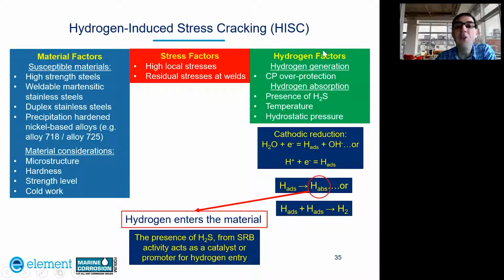So if we come to the hydrogen factor, we can split these into 2. So the first is the hydrogen generation, and this is due to the cathodic protection system and overprotection or too negative values generating hydrogen at the cathode. And then we can look at hydrogen absorption into the materials, and this is really dictated by firstly the amount of hydrogen that we've got at the surface and also the presence of hydrogen sulfide in the environment, the temperature, and also the hydrostatic pressure.